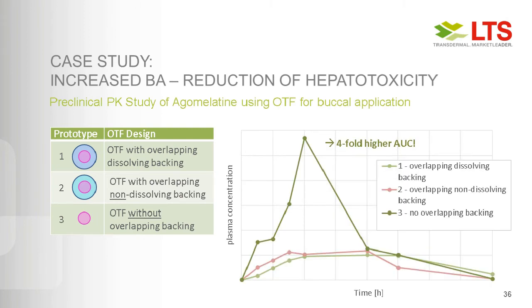And these were the results. When looking at the plasma concentration over time, prototypes number one and two showed a pretty similar drug release over a certain time, until the remains of the films were removed, about half of this curve here. So it has a constant delivery through the mucosal tissues, as targeted, as wanted. And when we don't use the overlapping backing, of course, the API is released throughout the whole oral cavity, and we have a maximum spreading over the surface area of the mucosal tissues, and therefore we can easily see here in this case the 4x increase of the AUC by prototype number 3. Of course, it was not the target one, but you can see here the difference between a buccal patch and a melt-away film.